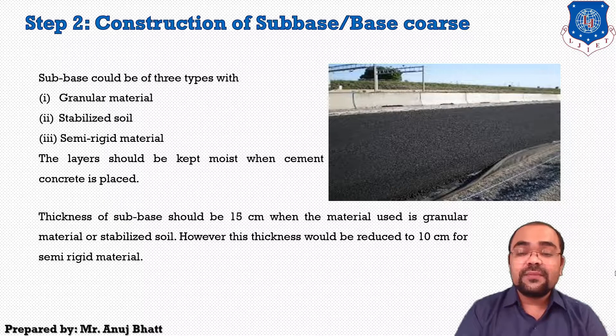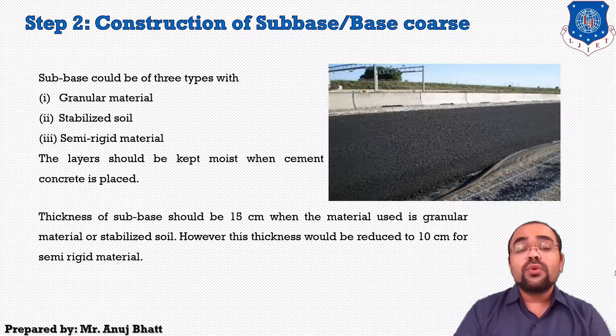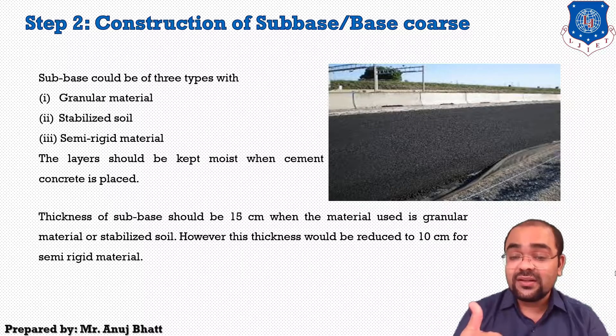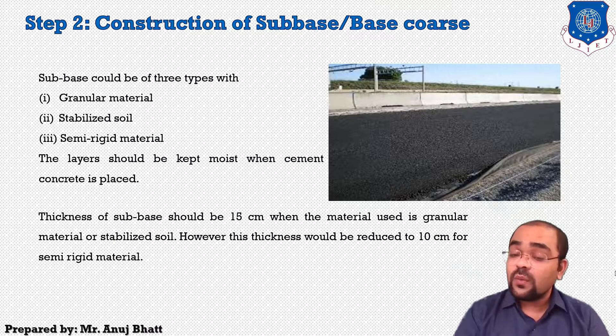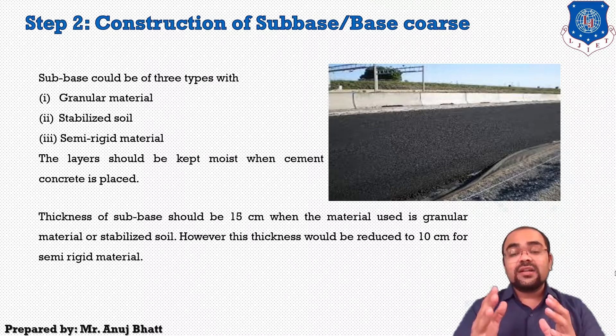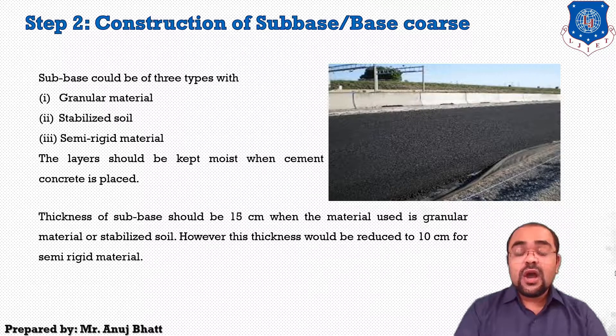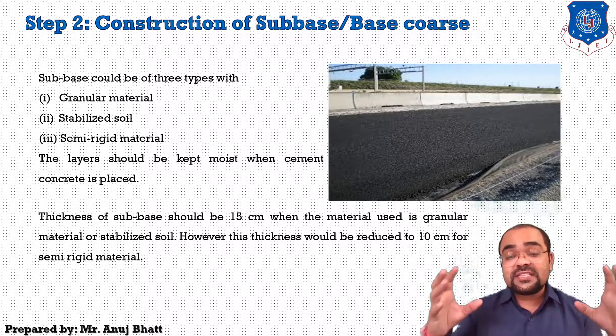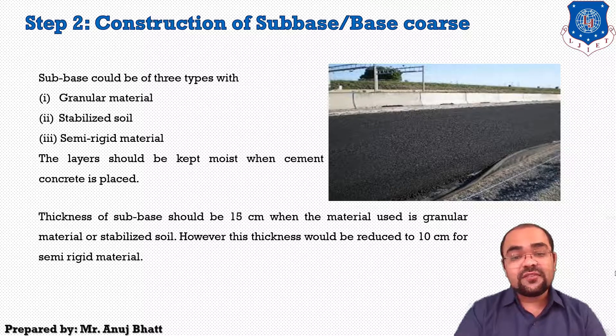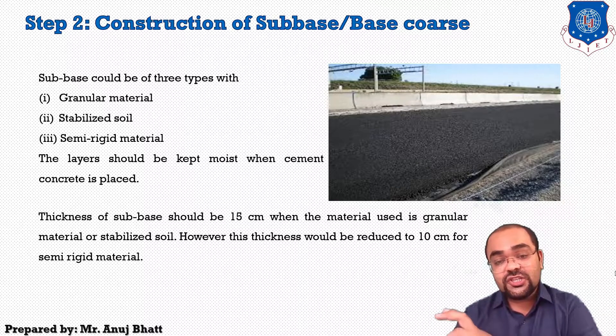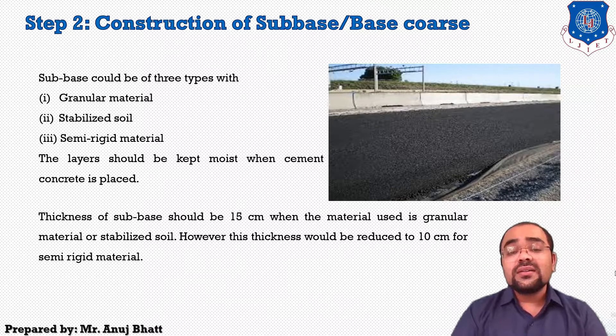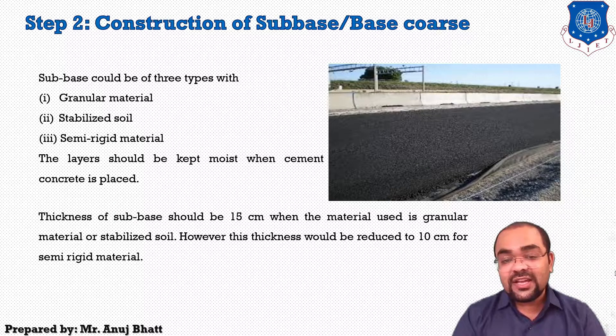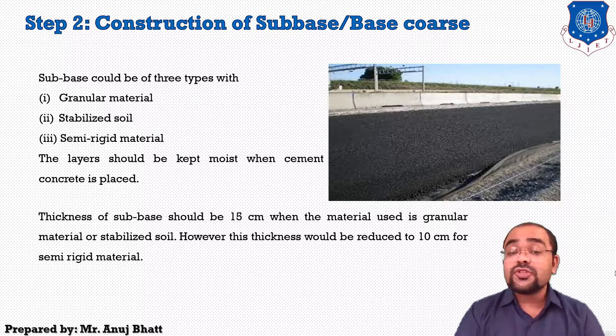For granular material, we can provide brick soling with one layer of sand under it, macadam, or well-graded granular materials. If using brick soling, one layer of flat brick soling with joints filled with sand under one layer of WBM material should be specified as per IRC 19:2005. The next subbase course can be constructed with stabilized soil — local soil or mooram stabilized with lime, fly ash, or cement to give a minimum soaked CBR of 50 after seven days of curing.